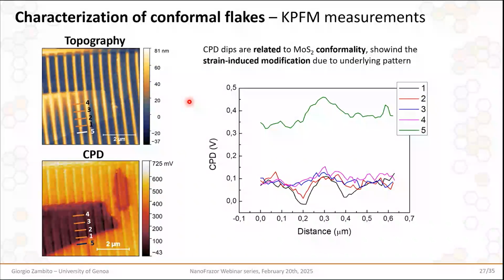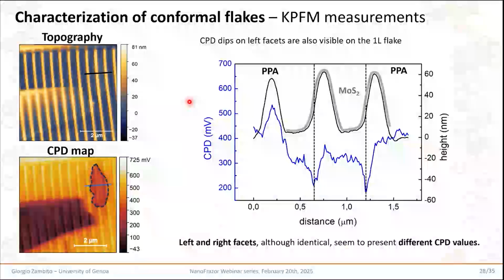And a similar thing we observe on the monolayer. For example, if we compare line profiles of topography and CPD from the monolayer MoS2 flake, we observe that again we have a CPD modulation that is in line with the underlying pattern, with the same periodicity. These modulations are around 130 millivolts, and again they are localized on left facets of the patterns, which is weird because we are patterning facets that are intrinsically and by design symmetrical. So why are we observing something asymmetric with respect to the single facets?